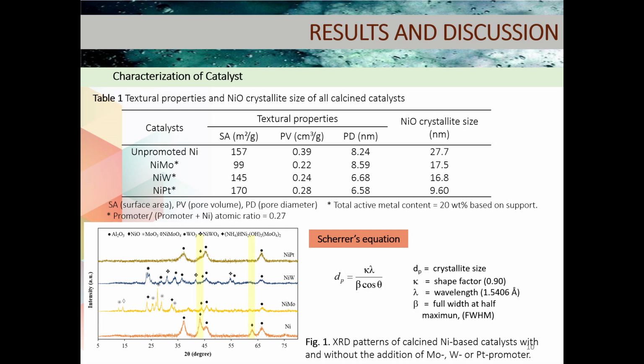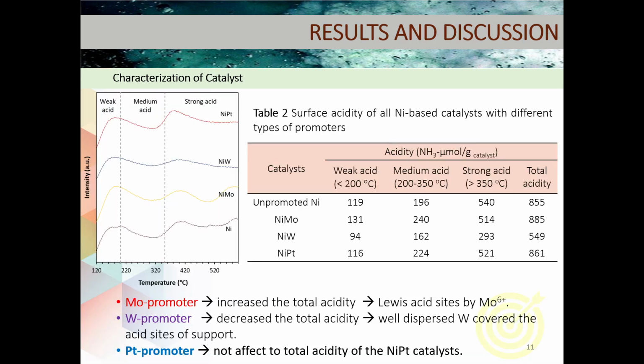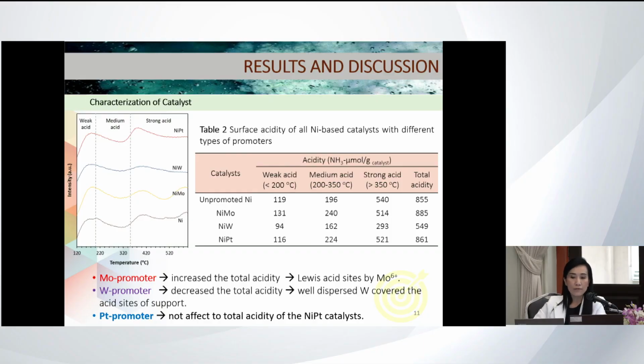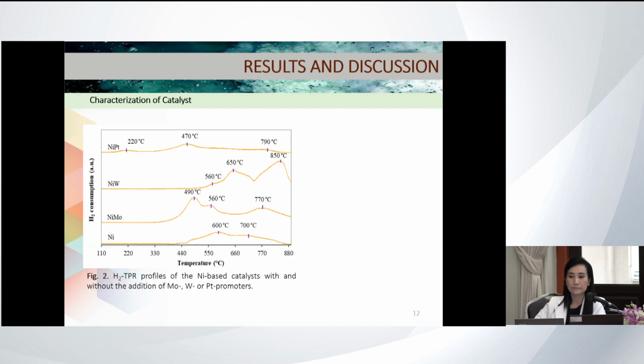the gamma alumina. And because the catalyst that is suitable for the hydrogenation is the acidic catalyst, this table shows the acidity of the studied catalysts, and it shows that when we apply the molybdenum promoter into the nickel catalyst, it shows the higher acidity because of the molybdenum oxide that shows the Lewis acid site, but the result is opposite for the nickel tungsten. It shows the lower acidity because the well-dispersed tungsten covers the acid site of the support. And the nickel platinum does not affect the total acidity of the catalyst.